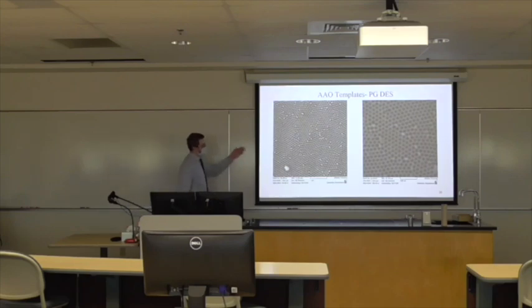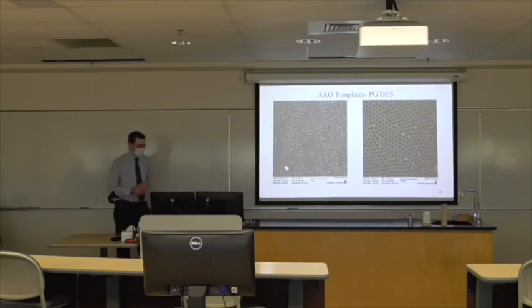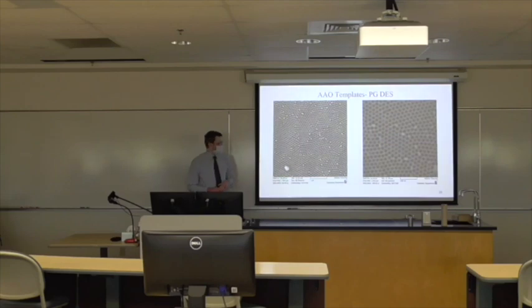As we can see from these images, we have a pretty clear ordering of the pores that are roughly 60 nanometers in diameter, as you would expect using 50 volts, from the direct proportionality of the voltage used and the diameter. And the polishing we had seen with the propylene glycol does not appear to have affected these very much. As you can see here, these look pretty good. These look closer to what Masuda and Fukuda had produced compared to the Whatman nanodiscs, as far as the general ordering and the structure here. This is with 99.99% pure aluminum, so the slightly better purity aluminum. And so yeah, these work pretty well.